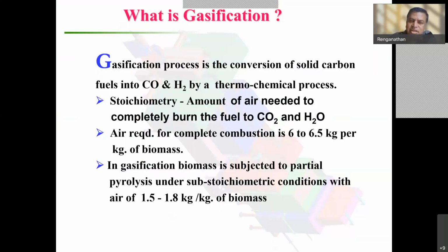What is gasification? Gasification is a process where solid carbon fuel is converted to carbon monoxide and hydrogen by a thermochemical process. Stoichiometry is the amount of air that is needed to completely burn a fuel into CO2 and H2O. Air required for complete combustion of biomass is about 6 to 6.5 kg. So 1 kg of biomass requires about 6 to 6.5 kg of air.